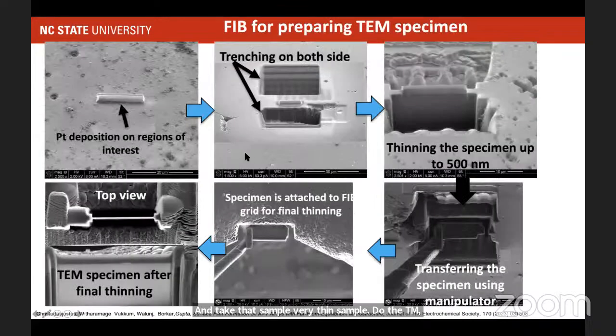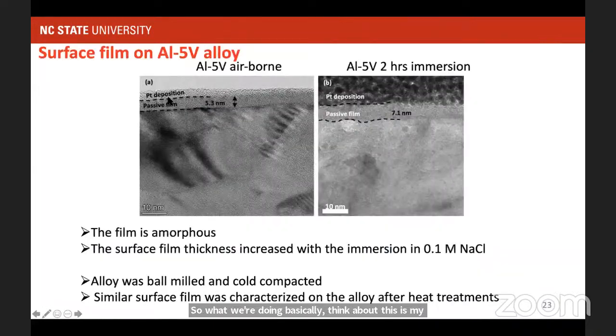So what we're doing basically, think about this is my sample, and we're looking at the cross section of the sample, right? So now here is how the passive film looks like. So this is aluminum 5 vanadium alloy. This is kind of two examples. One is just taking the material and putting it in air, right? We prepared the material and this had been stored in the glove box. And even in that high purity environment, as we discussed, right?